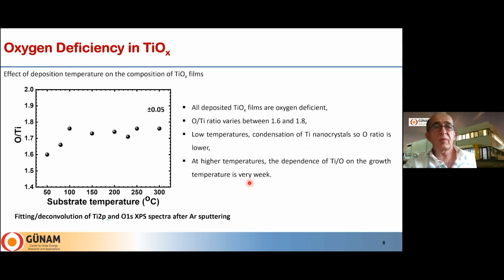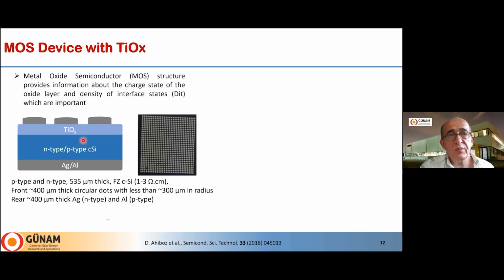So usually this titanium dioxide has some oxygen deficiency. Almost all of them have oxygen deficiency. In our case, we have a value of about 1.8 for this X in the titanium oxide formula, so it's in between 1.6 and 1.8. So after determining all these process parameters, we started looking at the electronic properties of these structures. So we fabricated some test structures, as you see here. And this is a kind of MOS structure, metal oxide semiconductor.